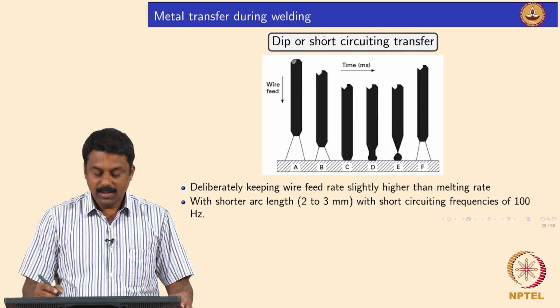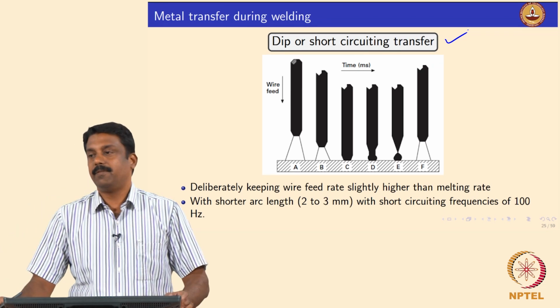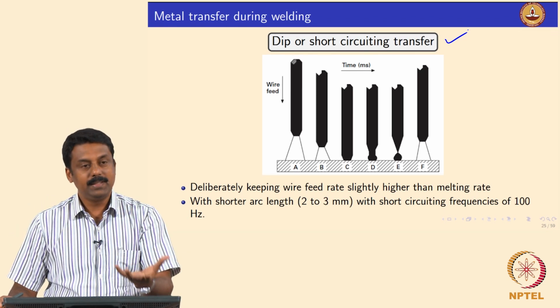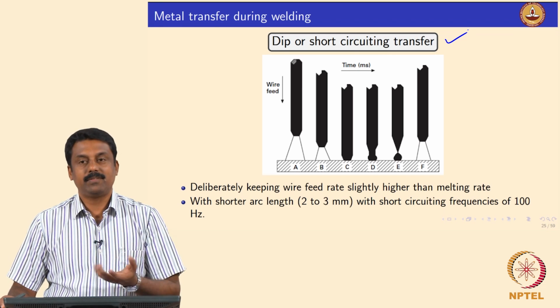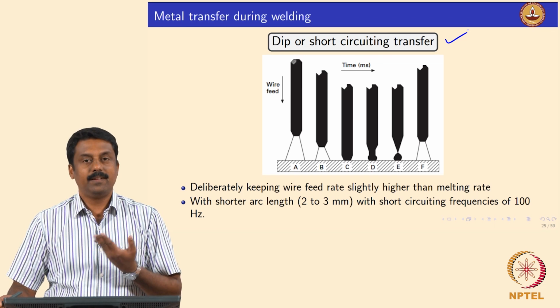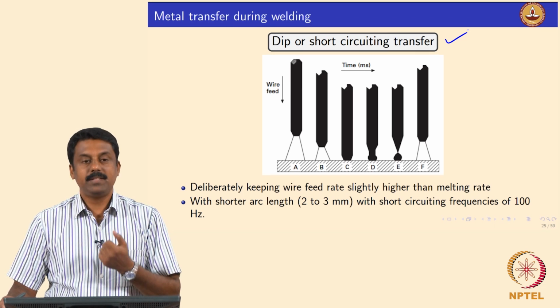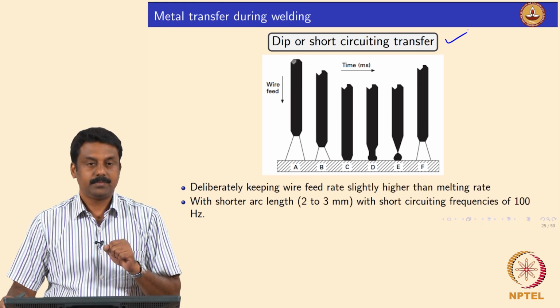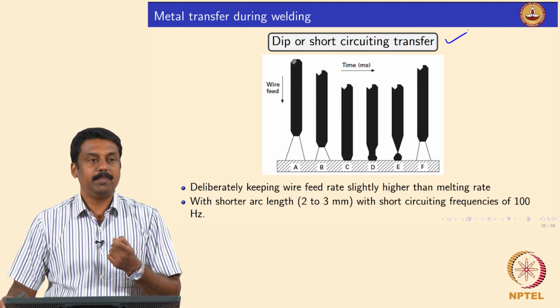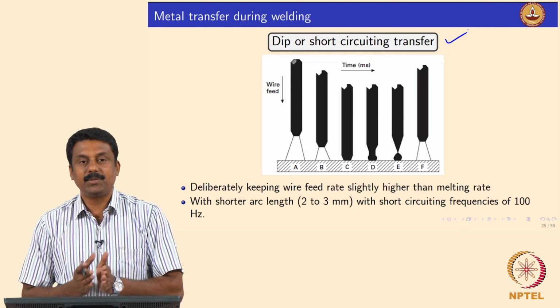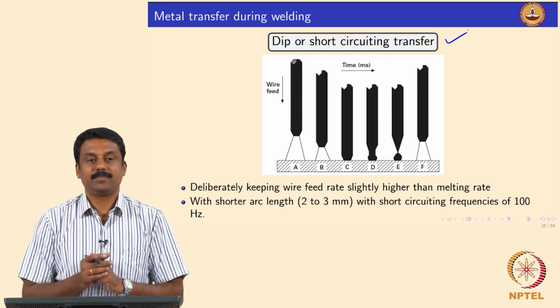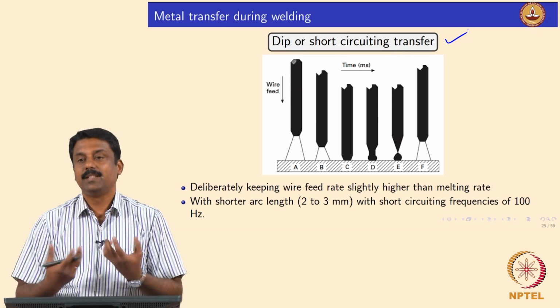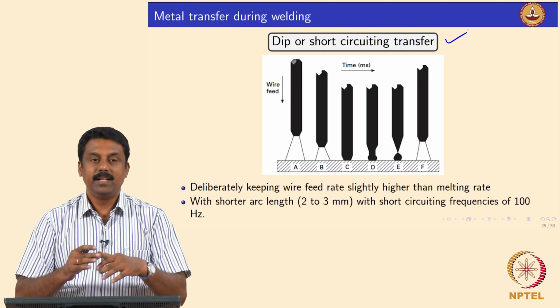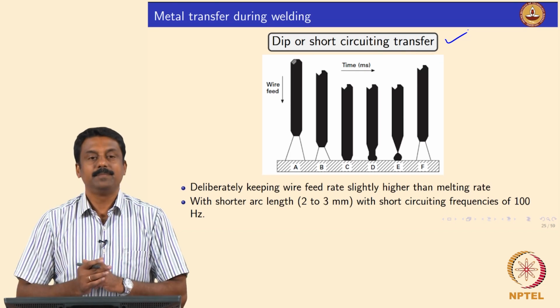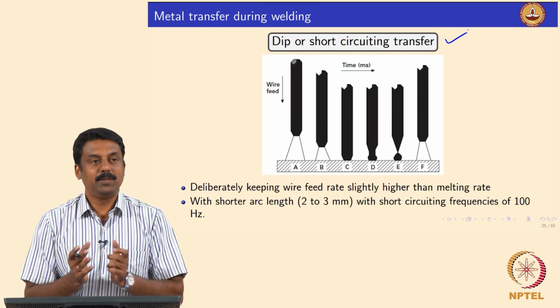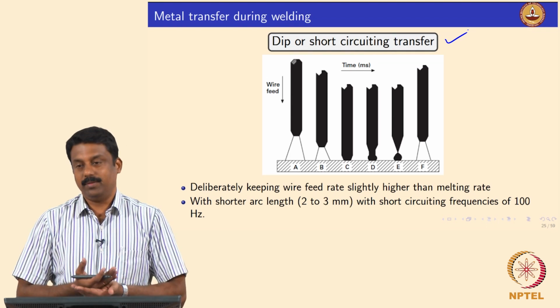Okay. So, this is a part of non free flight transfer. In free flight transfer, droplets are transported from the tip by free flight, is not it. So, you can also achieve the transfer by short circuiting. There are a lot of advantages having a short circuiting transfer. So, one of the major advantages is controlling the heat input. By carefully manipulating the event of short circuiting, we can switch off the arc momentarily, okay, so that when the droplet is transferred, it is transferred by surface tension of the liquid, no other factor. By doing so, we can reduce the superheating of the pool.